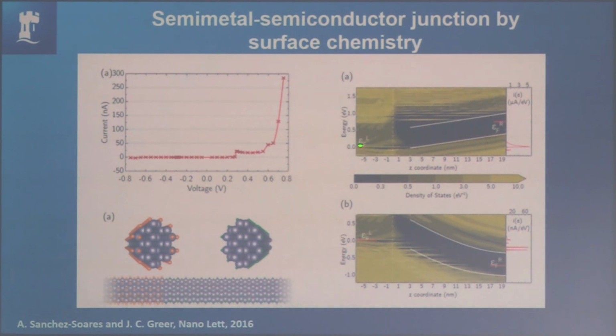This is basically the region of the thin film, or the nanowire in this case, in which the band gap has been closed, so I use one termination here. So you see it's metallic. The local density of states exists everywhere. On the other side, we let the quantum confinement do its stuff. It opens up the band gap, and as you see here, this is very typical of a Schottky junction, a metal-semiconductor junction. This is actually hole transport in this case, but when I finally start tunneling from the Fermi level into this valence band here, I get current. You get a very large current peak there.